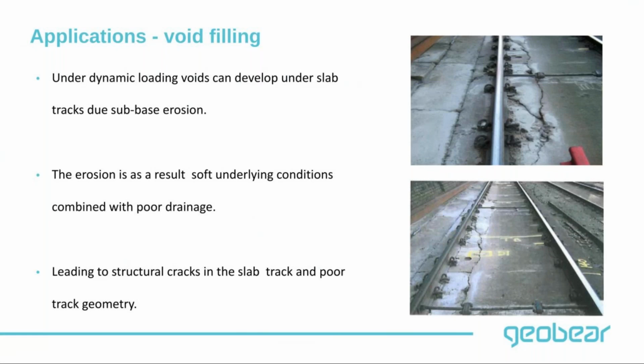You're always going to get some sort of deterioration. Especially if you've got soft underlying conditions combined with poor drainage, you would end up eroding the subbase underneath the slab track, and as a result you're going to end up cracking the slab. When you get that, you're going to lose your track geometry very rapidly, you're going to get track faults, and so on and so forth. Well, what can we do about it?